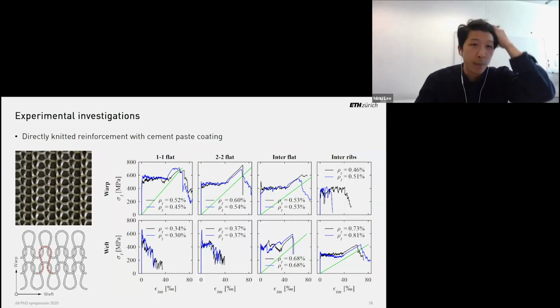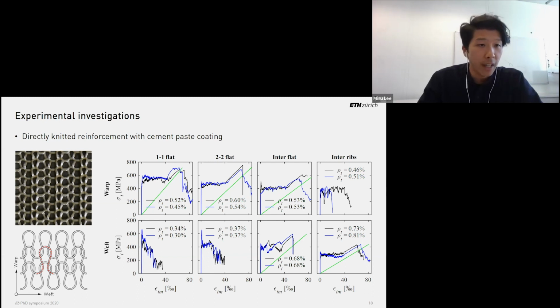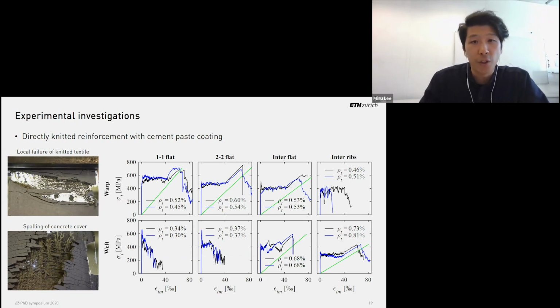So coming to the results, in this slide, we can see the load deformation behavior for all specimens with directly knitted reinforcement. Due to the knitted process, the structural behavior also depends on the direction of loading, which is called warp and weft, which refers to the direction of production. Although we could observe a hardening behavior for certain configurations, as we can see here, after cracking, the failure modes of the specimens were rather messy. There would be either local failure in the knitted textile, creating big holes, or spalling of concrete cover. And some specimens also failed shortly after cracking due to low amount of reinforcement content, as we can see in the bottom left corner.